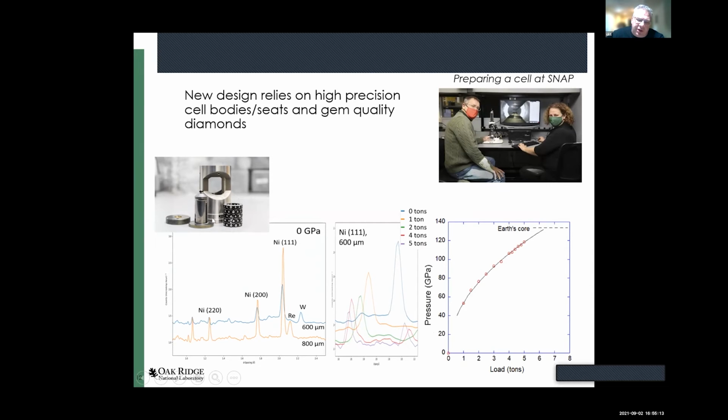So Riney has been working on a new design of cylindrical bearings that help move the piston back and forth. And actually, this provides very stable alignment. And most recently, we did experiments on ice up to 92 GPa and got good quality diffraction data using this type of design.